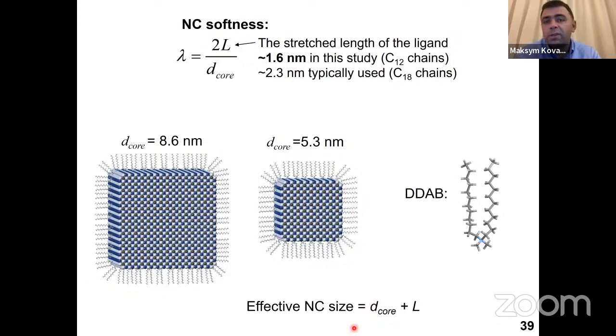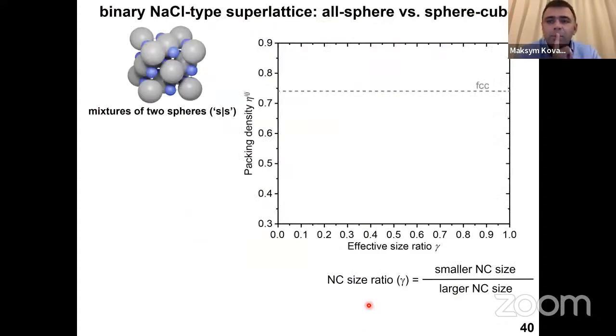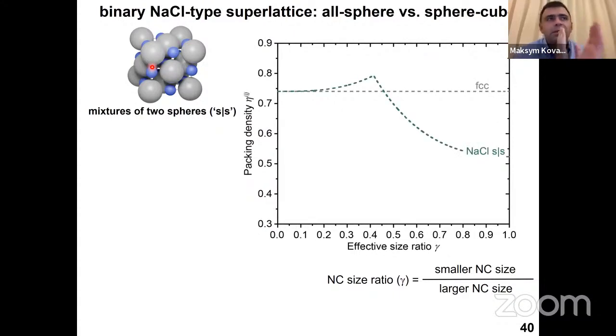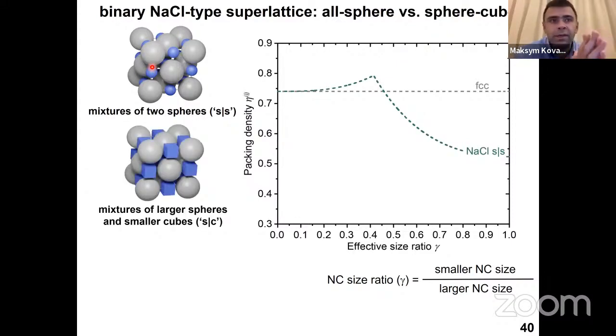So the effective size of the cube is the core plus the ligand length. And then we thought, okay, this lattice is known for spheres. Can we make it out of cubes? Now the rule of thumb here is the following: you need to mix the sizes of your spheres, or a cube plus sphere, in a certain range where the resulting packing density for this lattice will be the highest. Because unlike two atoms where you cannot really change the size, here you can.